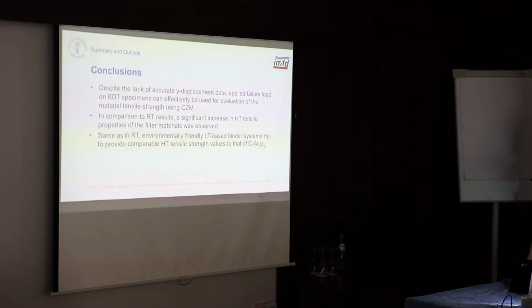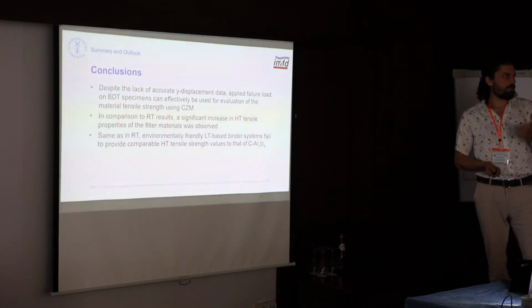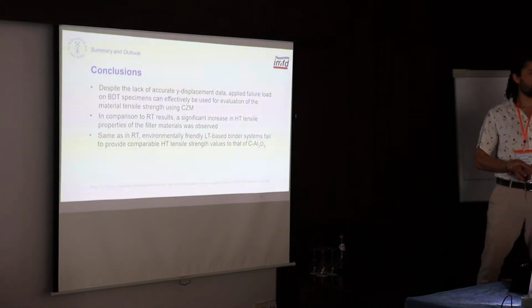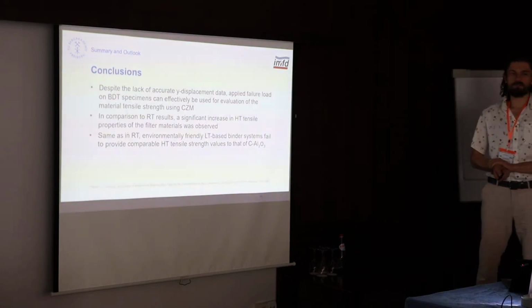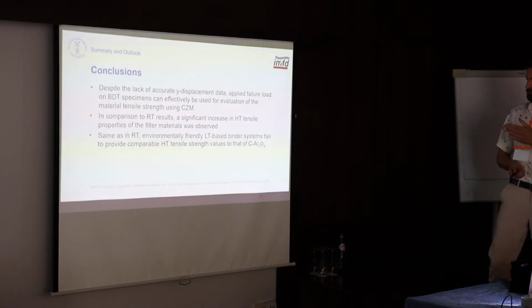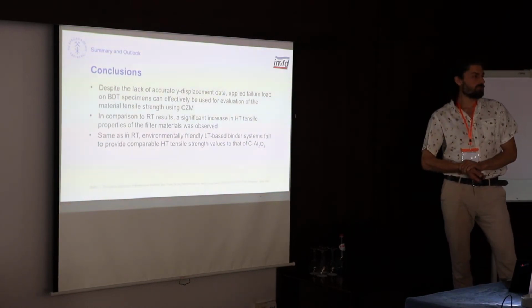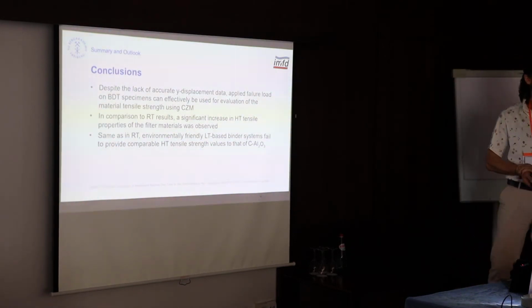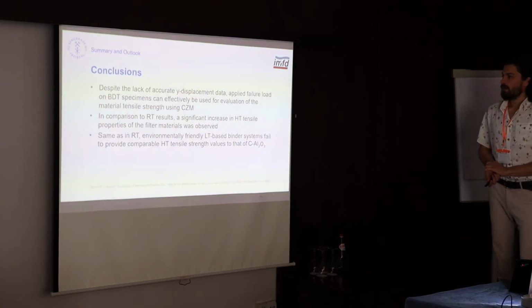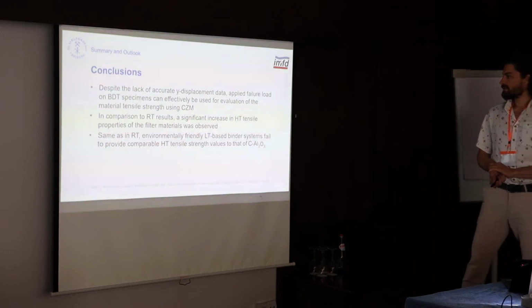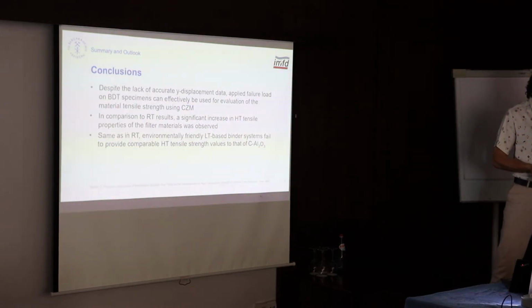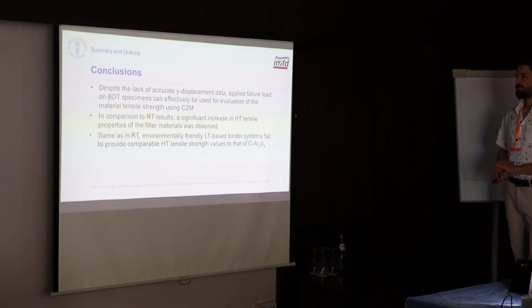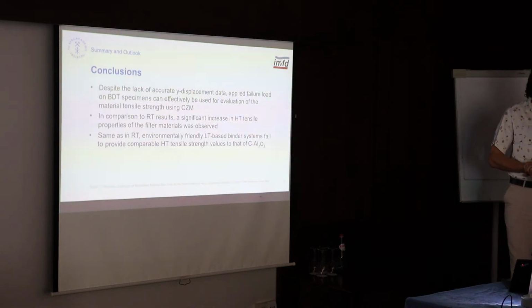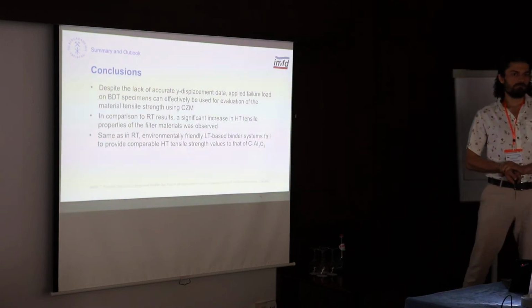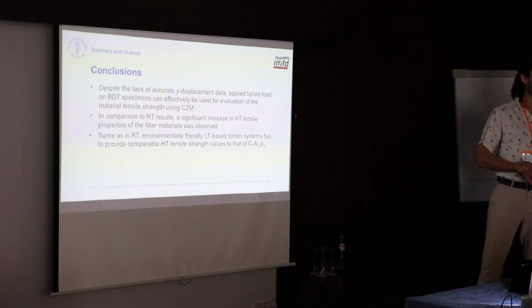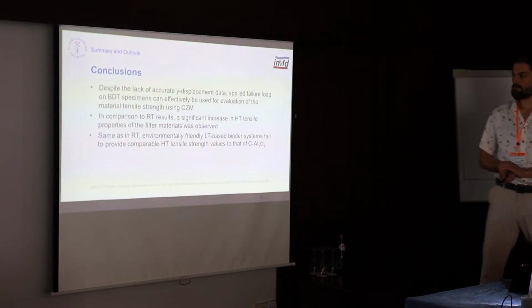So the conclusions from this work are that although I didn't have accurate Y displacement data from my experiment, I was able to use a cohesive zone model to find out the tensile strength of my filter materials. First of all, there's a considerable increase in tensile strength of the filter materials at higher temperatures, and it's also obvious that lactose and tannin-based binder systems cannot provide properties comparable to those of carbon bonded alumina, even at high temperature as at room temperature.